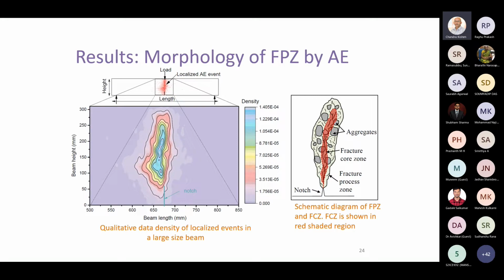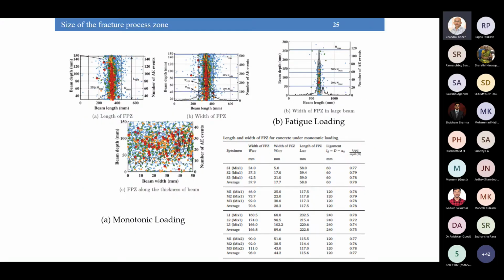Now from the acoustic emission events, we can also plot the density curves, the relative density of the localized events, and we get a picture of the shape of the fracture process zone. The morphology of the fracture process zone can also be obtained from the acoustic emission events. Here, the size of the fracture process zone is calculated using the distribution of the acoustic emission events. So we draw a histogram. This is the front face, that is the beam length, what we are plotting this on, and this is the depth of the beam. So here we are drawing a histogram.